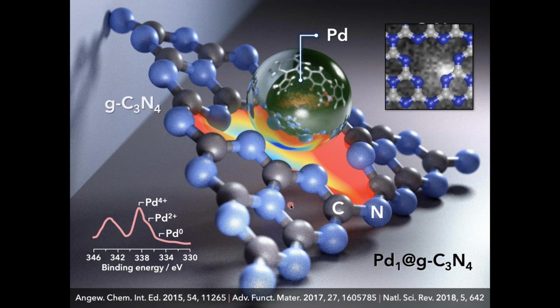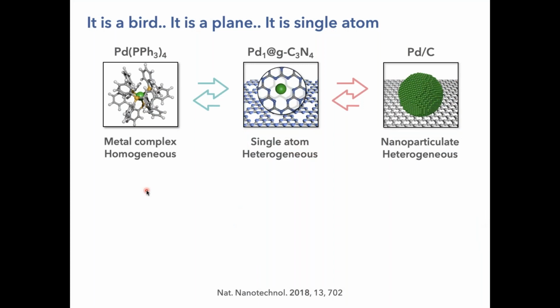And the fact that there is this very strong interaction between palladium and the host, the nitrogen in the host, leads to the fact that palladium is highly charged. So you have cationic species rather than metallic species. And this opens really very nice opportunities to utilize these systems in replacing homogeneous catalyst because actually the solid host acts as a ligand to the palladium atom, which is charged, resembling a lot the structure of this triphenylphosphine that is used classically in many different applications in homogeneous catalysis. So this single atom heterogeneous catalyst is in between a homogeneous metal complex and a nanoparticulate catalyst.